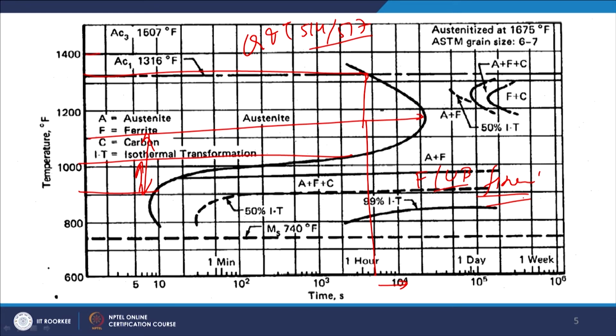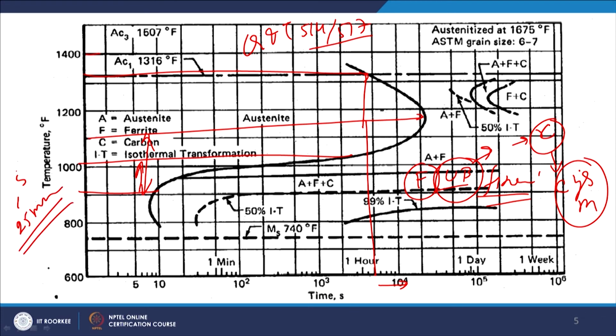So, ferrite and the upper bainite at the same time, whenever this kind of transformation takes place, involves the formation of the ferrite from the austenite with the rejection of a lot of carbon into the austenite, and that is why on subsequent cooling we may find the formation of the high carbon martensite. So, in case when thick plates like 25 to 50 mm thick plate are welded, we may find a situation where no transformation of the austenite into the softer phase takes place, but whenever the austenite transforms into the ferrite, the carbon is rejected into the austenite, and that in turn subsequently leads to the formation of the high carbon martensite. So, this will be leading to the formation of the ferrite plus high carbon martensite.